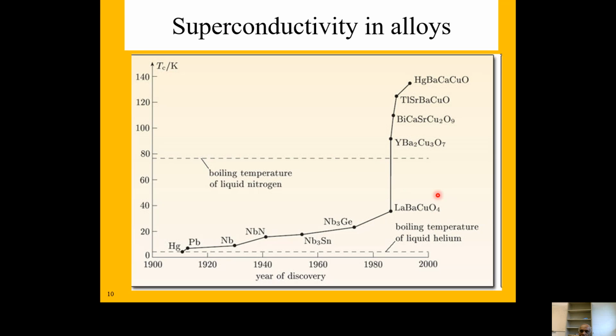Then there was a lot of effort at this point to try similar materials, replacing these elements by every possible element in the periodic table. Then all of a sudden, around that time, they found Tc around 90 Kelvin for this special material called YBCO, yttrium barium copper oxide. That's the first time you could see Tc above the boiling temperature of liquid nitrogen.